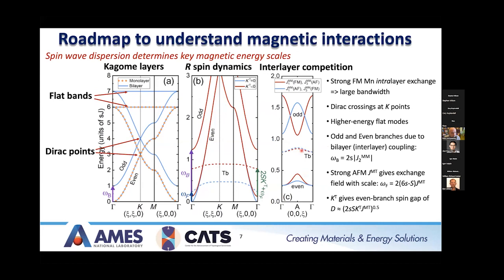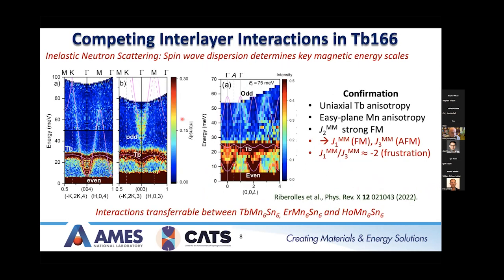Right, so you get these odd and even branches due to the bilayer coupling, which is set by this energy scale here. The strong anti-ferromagnetic interaction between the manganese and the rare earth gives an exchange field with a scale of JMT, but modified by the difference in the overall moment here. And then the rare earth anisotropy here gives the even magnon branch a spin gap on the order of the square root of JMT times KT. Okay. So sorry, I kind of swallowed a frog over the weekend, so I'm a little rough here. Okay.